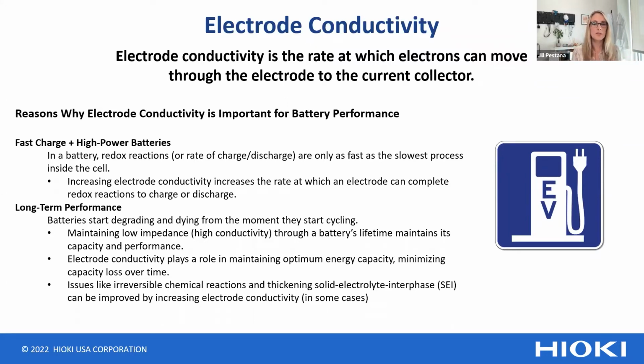And so issues also like irreversible chemical reactions and thickening of the solid electrolyte interface, or SEI, can be improved by increasing the electrode conductivity in some cases. There are cells, like I'm pretty sure LTO cells actually don't have an SEI on the LTO, but other cells like graphite-based, silicon-based, even for a cathode like a nickel-based cathode, LFP-based cathode, those form what's called a CEI, and increasing their conductivity can help mitigate the issues with the insulative CEI or SEI thickening over time.